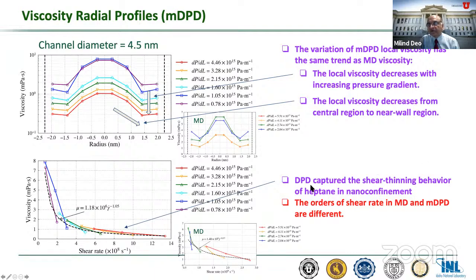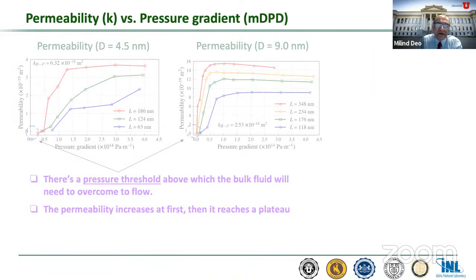So the higher scale models, which we need for validating or for comparison with experiments which we can only do at certain scales, capture the behavior reasonably okay, but it should be noted that it's not all perfectly scaled. We do have some changes because of the orders of shear rate in the MD and the DPD.